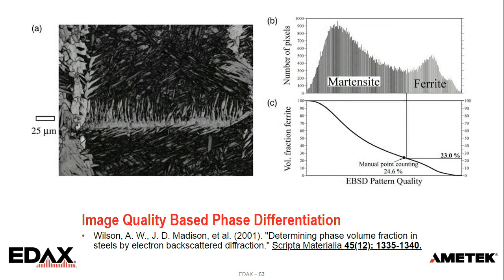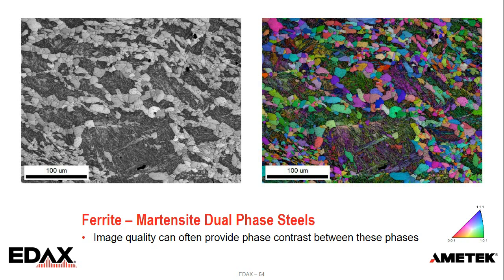And so traditionally, there have been a couple of approaches, and one that comes from about 20 years ago from Alan Wilson and George Spanos at NRL was looking at the image quality difference between the martensite and ferrite. This is one that's been used quite a bit. You can see there's a bimodal distribution. You can figure out where you want to draw a line. This is an example with our Velocity CMOS camera, where you can clearly see the difference between the ferrite and the martensite, both by image quality, how bright the grains are, but also the shape of the grains. This is used because it is an easy example.